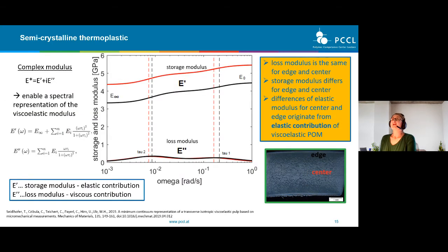So we took these creep measurements to calculate the complex modulus, which consists of the storage modulus and the loss modulus. And with the formulas down here, we enabled a spectral representation of the viscoelastic modulus. And in the graph here, we can see the storage modulus, which is the elastic contribution, and the loss modulus, which is the viscous contribution. And in the graphic, you can see that the loss modulus is the same for the edge and the center, which you can see down here in the graph. And the storage modulus differs for edge and center. So the differences of the elastic modulus for center and edge originate from the elastic contribution of the viscoelastic POM.